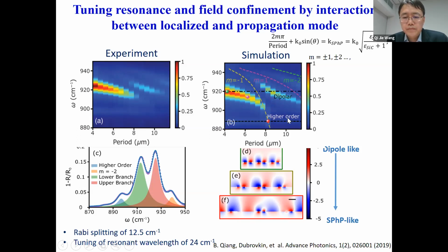and around 890, this is a higher order localized mode. And this yellow curve, red curve, and the green curve show the dispersion curve of the surface phonon propagation mode. And you know, they are coupled because of a relatively strong coupling. You will see a mode splitting here, the Rabi splitting. So we get a good number of Rabi splitting, about 13 inverse centimeter.